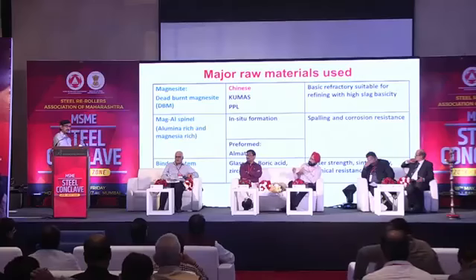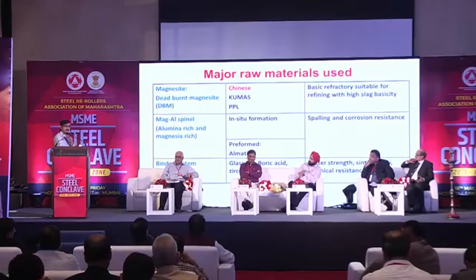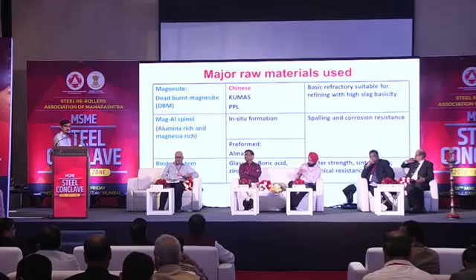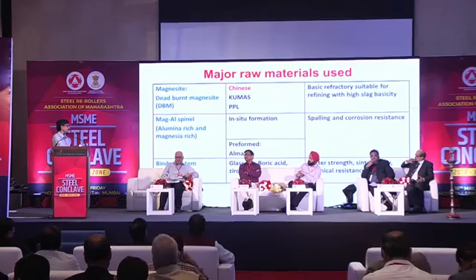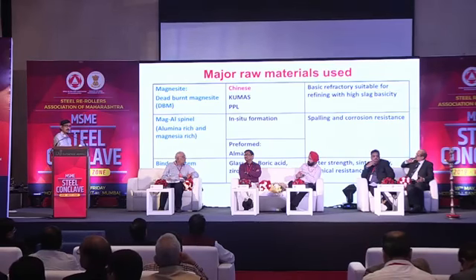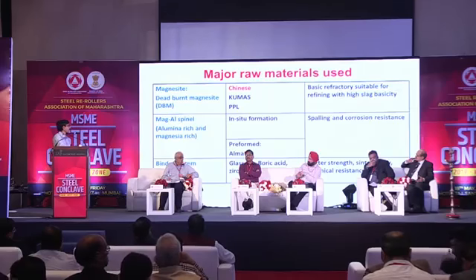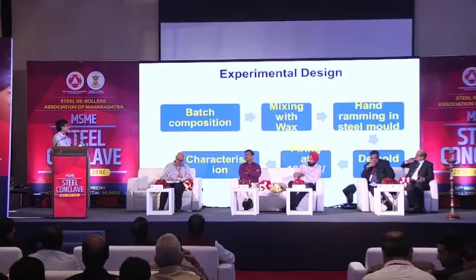And then the spinel also, we use the Almatis spinel, and to reduce the cost we have also tried in situ spinel in the batch. That means if you use alumina, you can develop the spinel in situ, in which case the cost will be low. And we have worked on some binder systems also. So this is a basic experimental design.